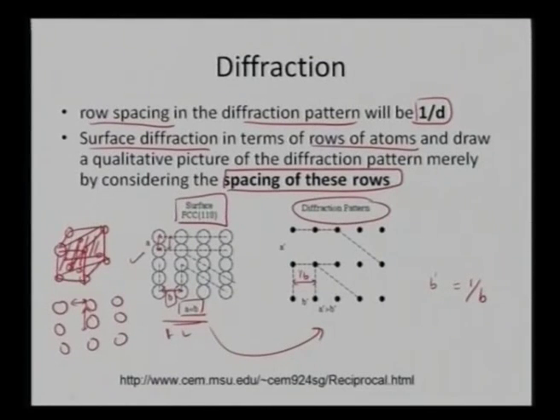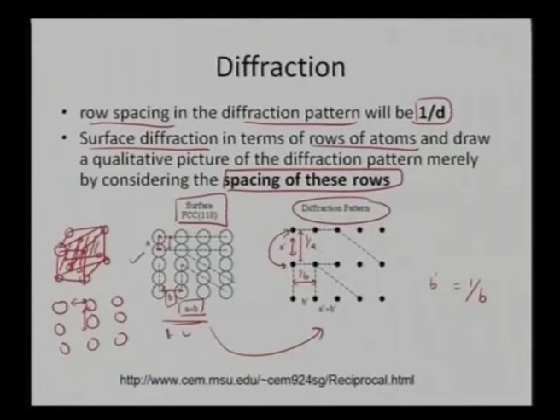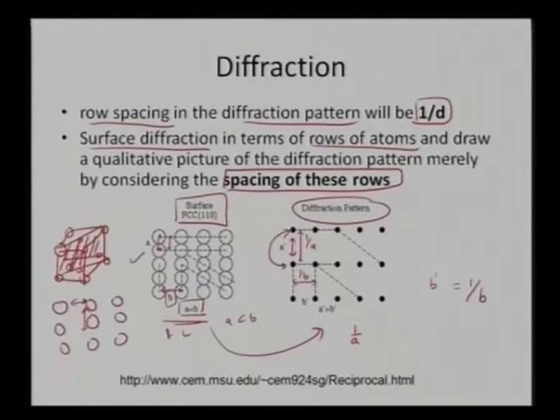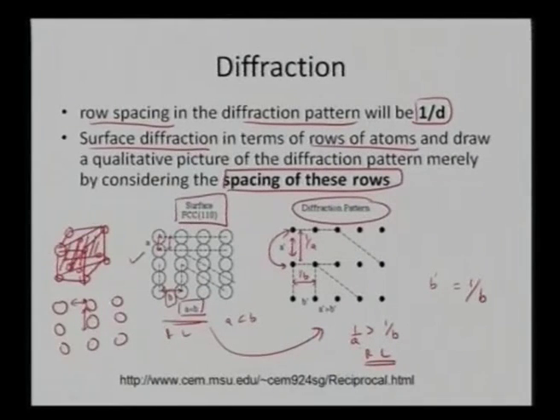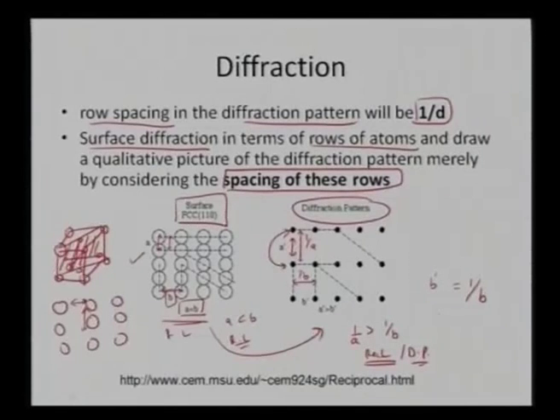Once I bring it to the reciprocal spacing, keeping b constant and representing it as b* = 1/b, I can see that in the real lattice I had a closer than b. But in diffraction, a goes much farther apart — 1/a has become much more sparse and spread out. In reciprocal lattice spacing, since a < b in real space, I now get 1/a much greater than 1/b.